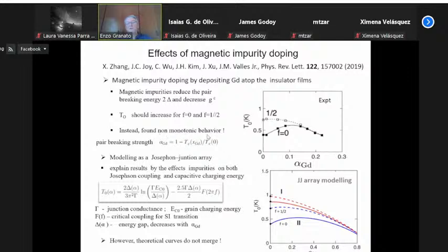Instead, what we found is non-monotonic. So here is the activation energy as a function of the concentration of magnetic impurity. For zero field, the activation energy first increases and then decreases. For frustration 1/2, it increases slightly, then decreases and vanishes at some particular value.